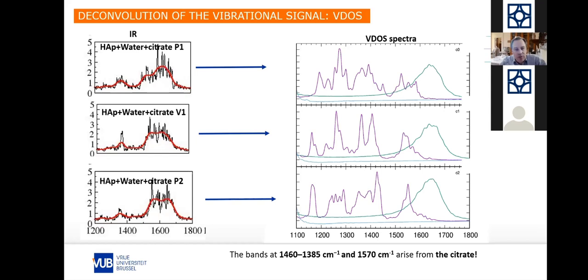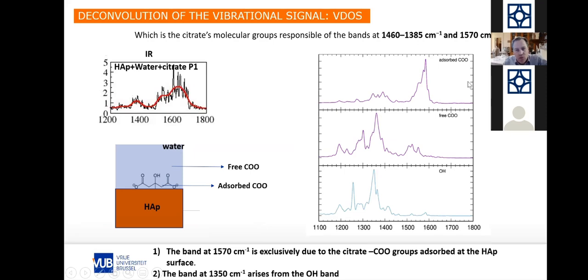For the different families, we can isolate the vibrations which are attributed only to water, to the citrate here in purple, and to the solid, our hydroxyapatite, in blue. For the three orientations, we can pin very precisely which band corresponds to which vibration. This is quite powerful. If we analyze that, we can say that our band at 1570 is associated with the citrate carboxylic group adsorbed on hydroxyapatite, and the 1350 arises from the OH band in the hydroxyl group. So we adsorb it like this. This is finally the final geometry that we obtained.